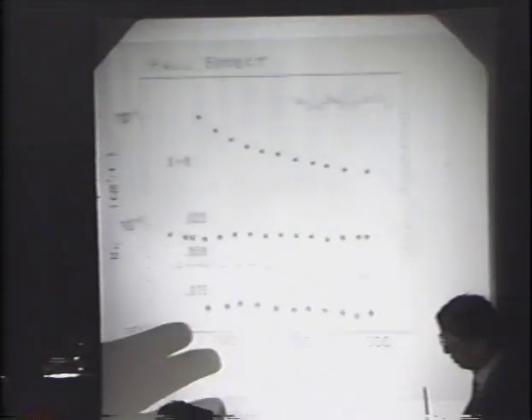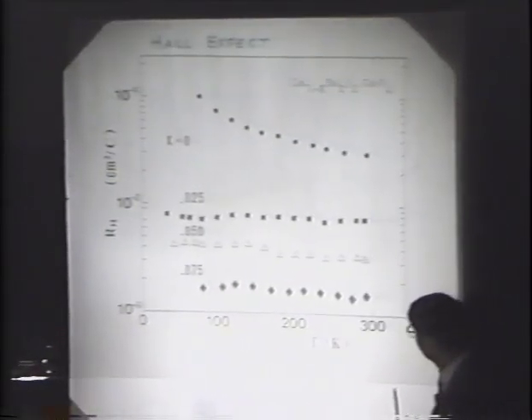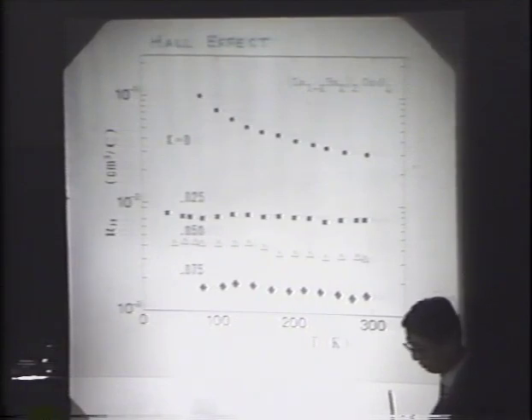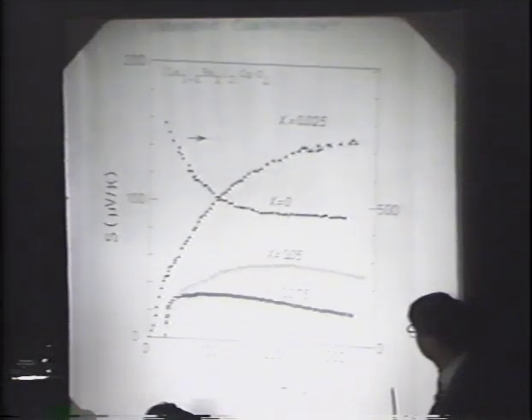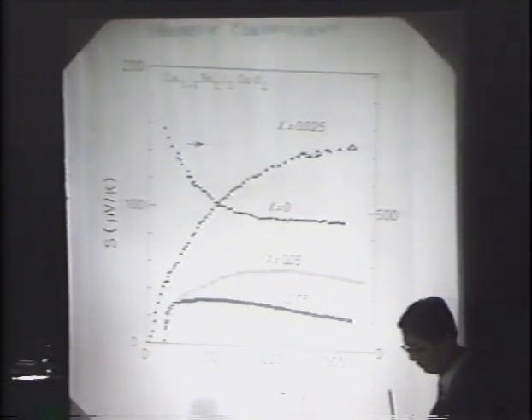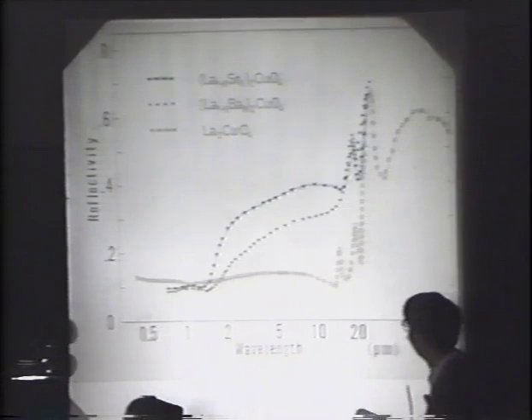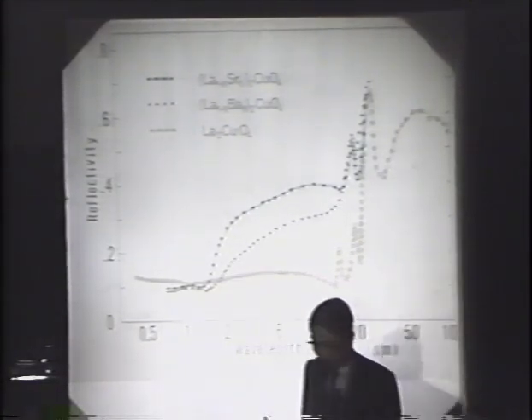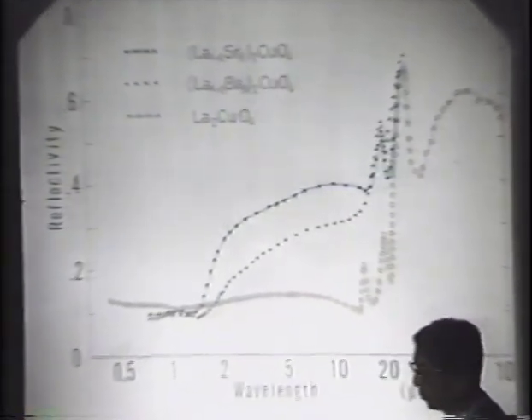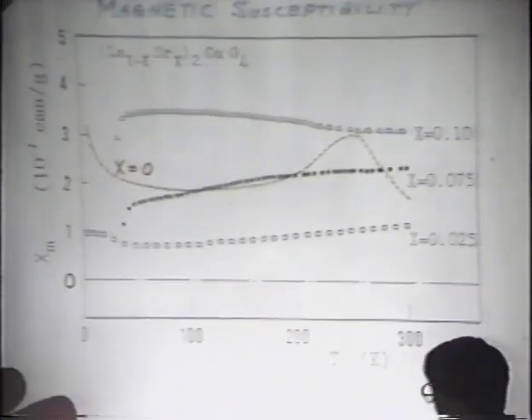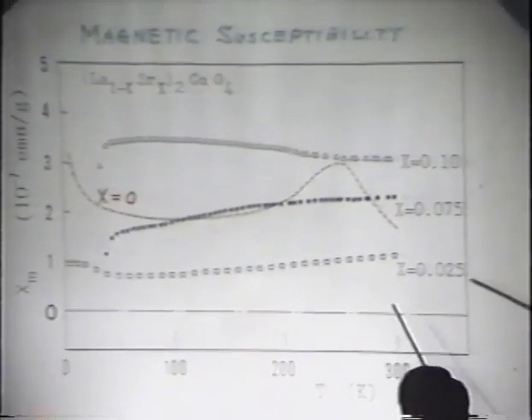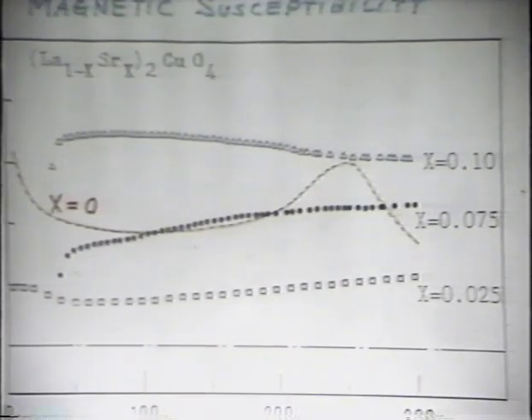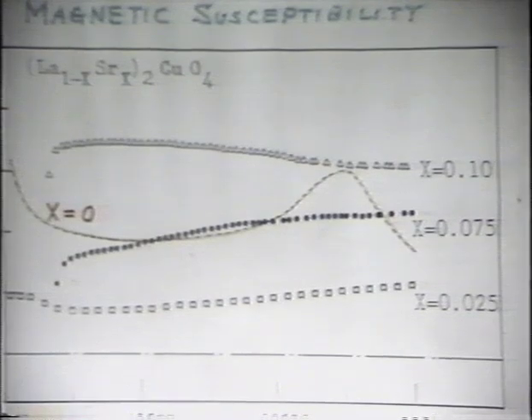Resistivity, Hall effect: carrier concentration increases with increasing doping. Seebeck effect, next. Plasma reflection. Omega P is almost 1.5 micron. Paramagnetic susceptibility. You see, this is x equals 0. The paramagnetic susceptibility increases with increasing doping.